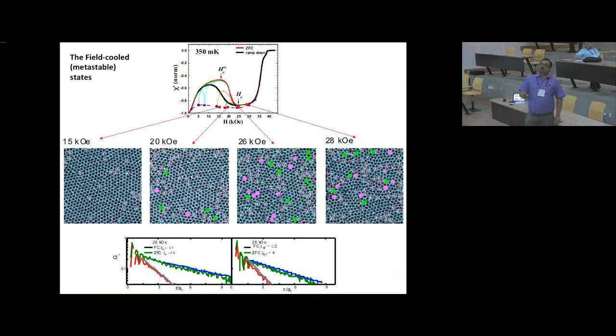For example, the 15 kOe state, which should have been a perfectly ordered state, here I see dislocations. At the 20 kOe state, where I should see only dislocations, I see disclinations. But recall that all these states can be annealed by applying a magnetic field pulse. If I apply a magnetic field pulse, they will go and join this state that I have shown you before. And yes, I think that answers your question. We have these glassy states everywhere. This is not a liquid in the conventional sense.